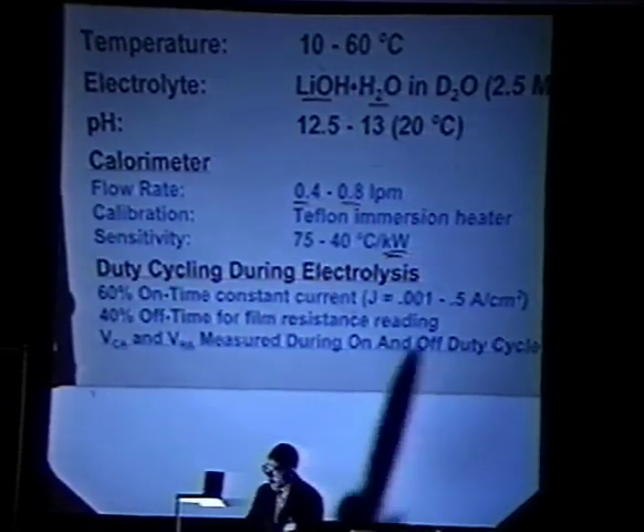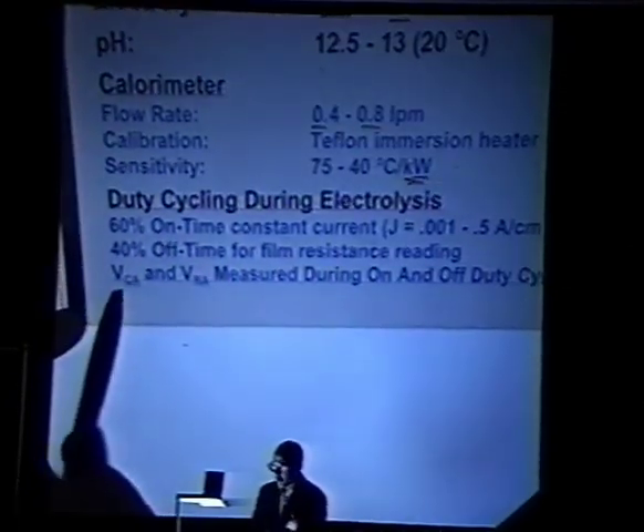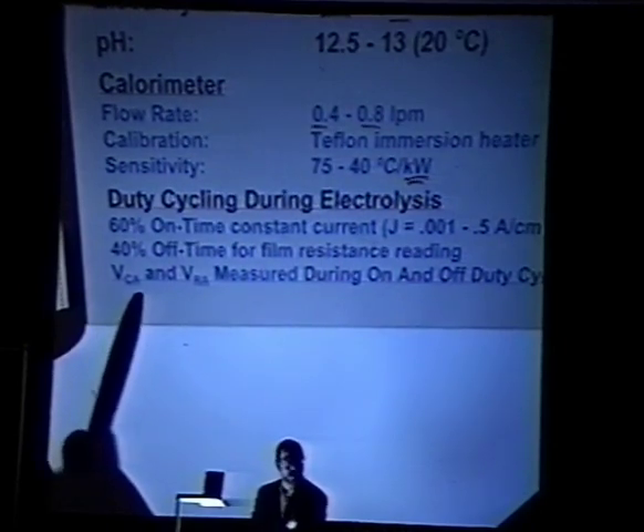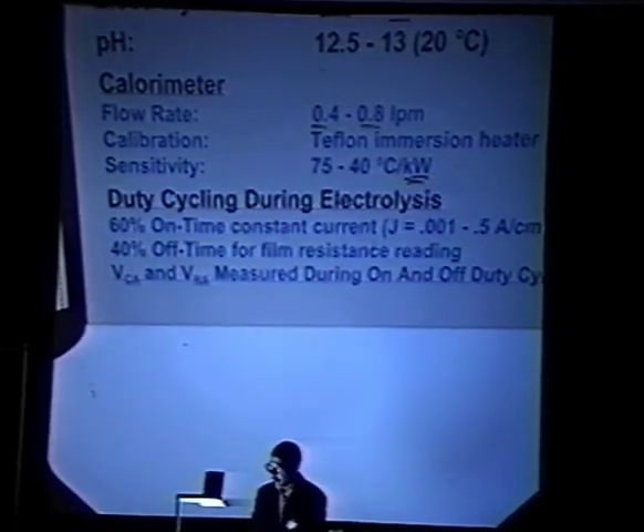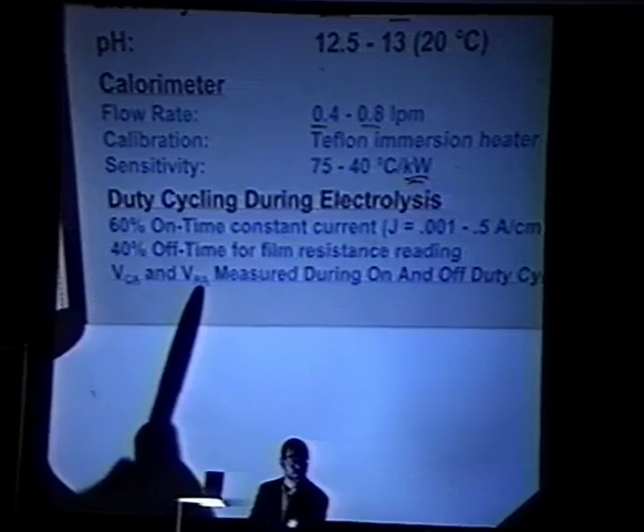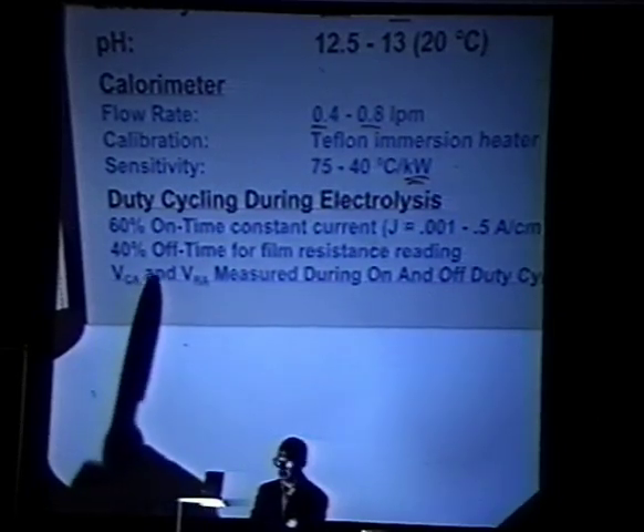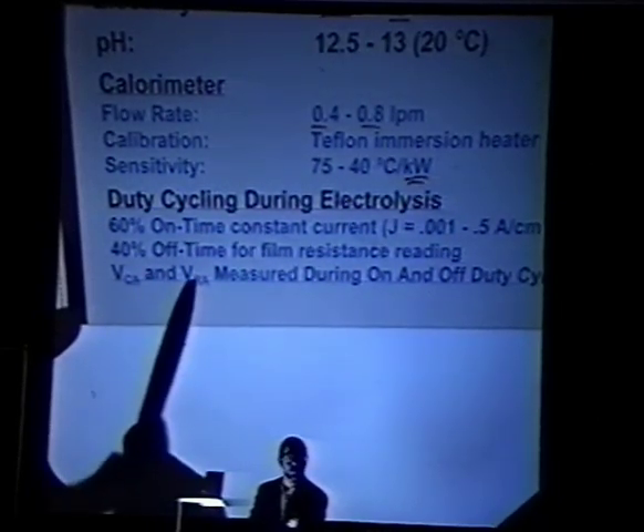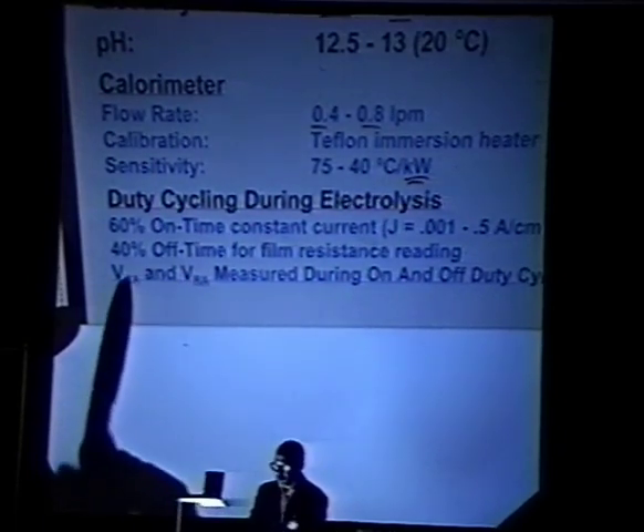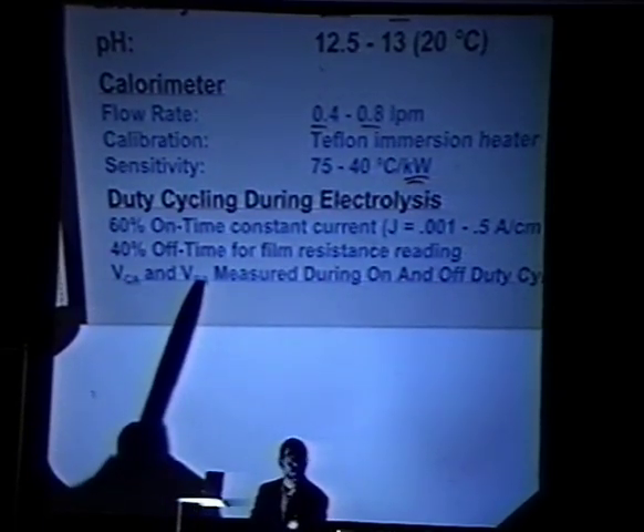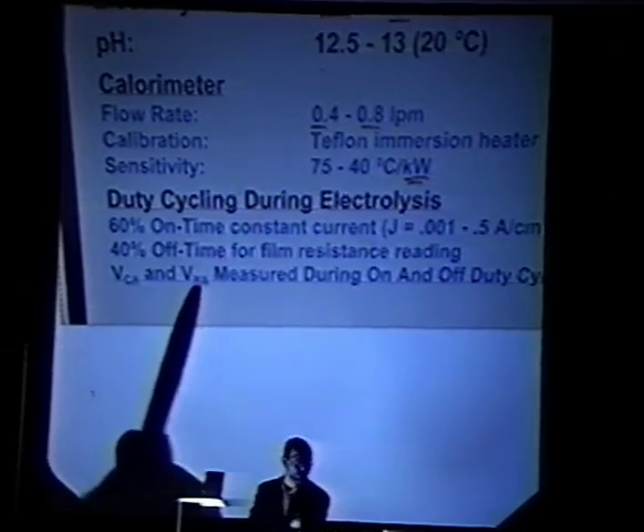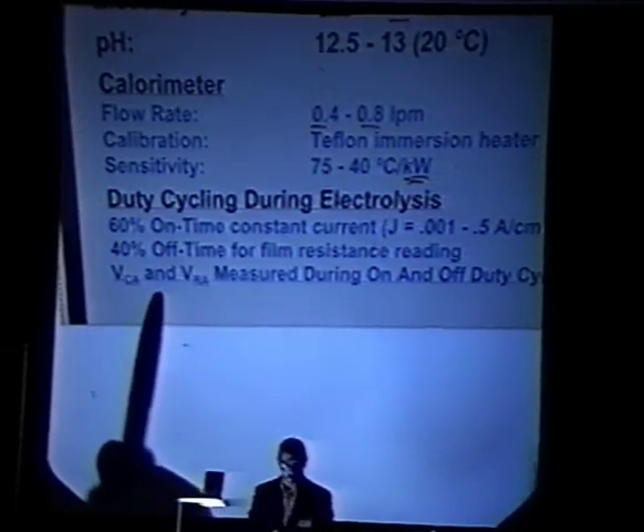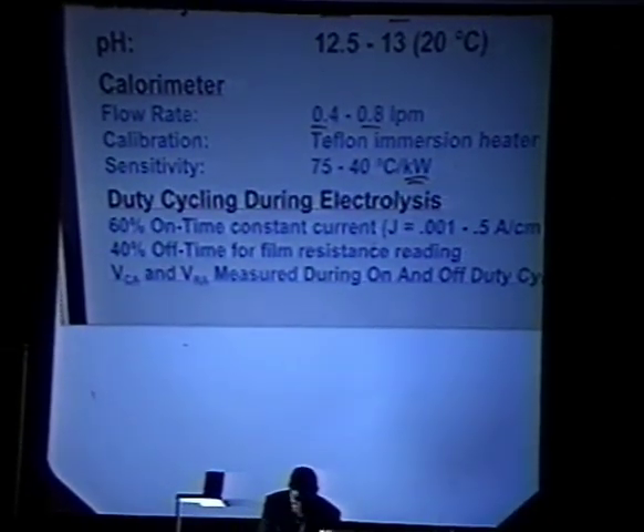Two of the things I'm going to focus on a little bit later is what I call the VCA. This is the cathode to anode potential and the reference to anode potentials. Those are two things that I found out much later, digging into those that did not run, that there are some central voltages that tend to show up when this thing is going to fire and when it's actually producing heat. And there's certain voltage ranges that don't work for this particular system. Okay? And again, just to remind you what that is, let me pull out that one figure.